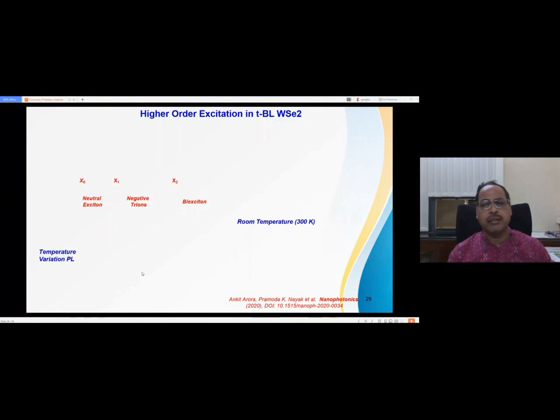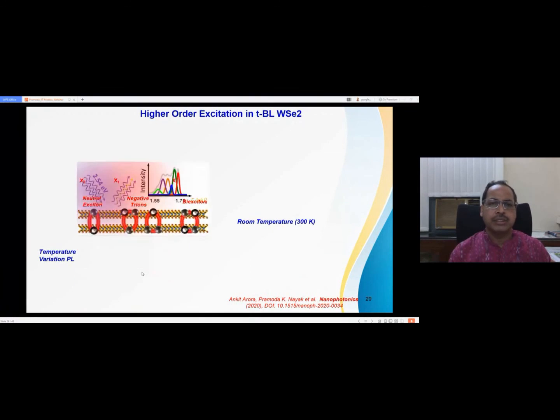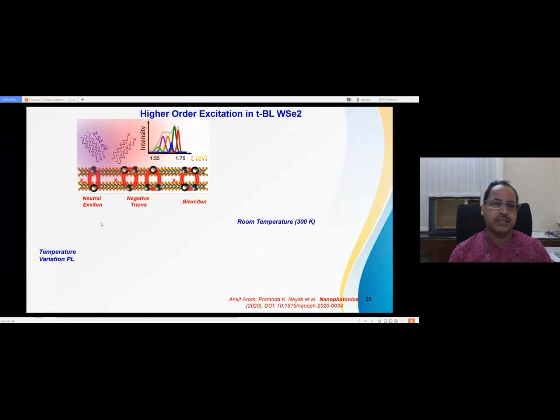So we also worked on bilayers. This was about a heterostructure. We also worked on the twisted bilayer WSe2. So we find many very complex features. So this is the neutral exciton. This is an electron hole pair. In comparison to the neutral exciton, if an extra electron is added, either from the substrate or from the other layer, you can get the negative trion, a higher order complex. We can have the biexciton also, electron hole pairs, biexciton also we can get.